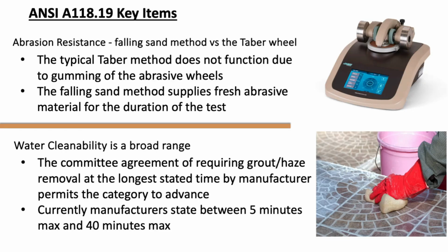And then the water cleanability, there was a broad range for that testing. So the committee agreement required grout haze removal at the longest stated time by the manufacturer permits the category to advance. Currently manufacturers, and there are many of us out there, state anywhere between 5 minutes max to 40 minutes max to be able to clean up the grout haze.